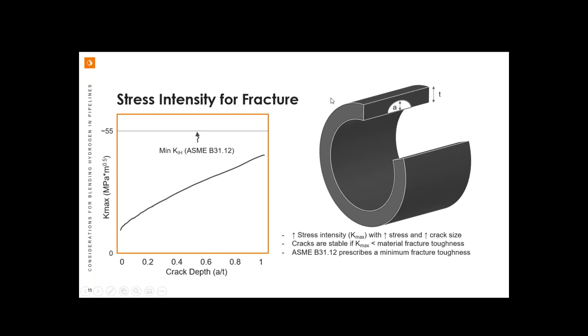Of course, we have a whole field of study for this, which is fracture mechanics. And just as an example, if we have a section of pipe with a long seam weld, and there's a flaw of known geometry, this happens in pipelines, and we have a hoop stress that's applied really to pull that long seam weld apart. Well, we can model this by calculating a stress intensity. We know that intensity changes with increasing hoop stress or pressure, as well as the crack size or the flaw size. And so here's an example where we take a constant pressure and we would plot the severity of the stress intensity versus that depth of the crack. And ideally, if nothing else, we want to make sure that that value is less than the demonstrated fracture toughness of our steel, which by the way in B31.12 would be about 55 MPa root meters.